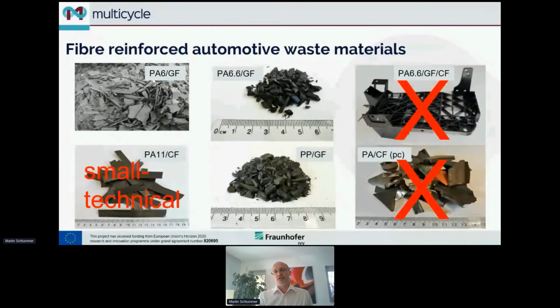And one of our most wanted materials, the polyamide with carbon fibers from post-consumer, was supplied. It was of course well characterized up front, and we unfortunately saw that neither the polyamide content was good enough, nor the carbon fiber content, with not only carbon fiber but also glass fibers.